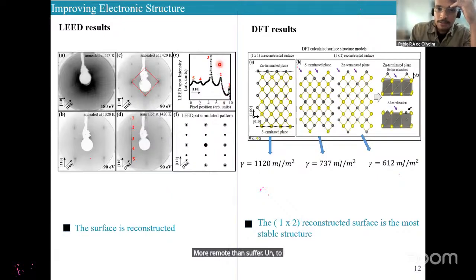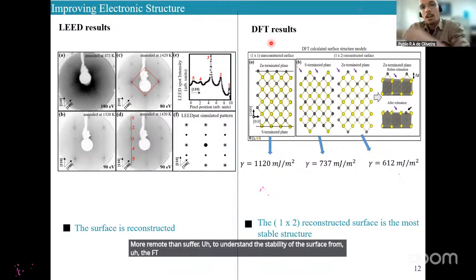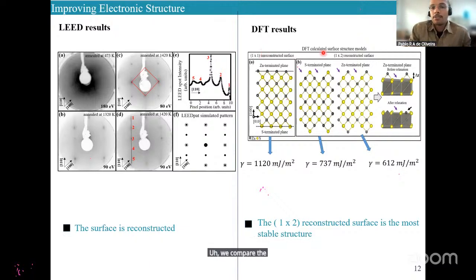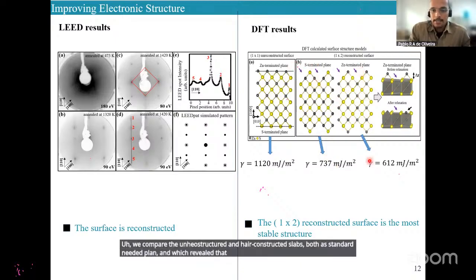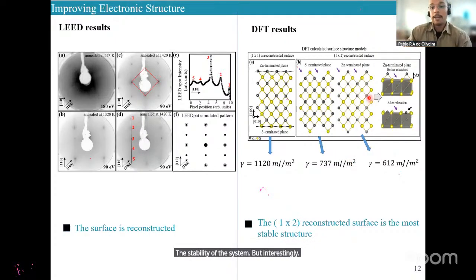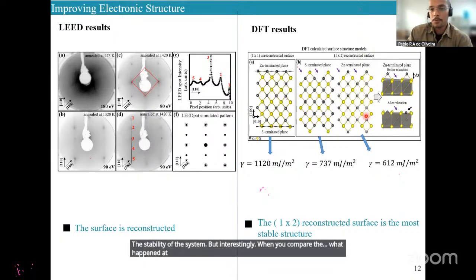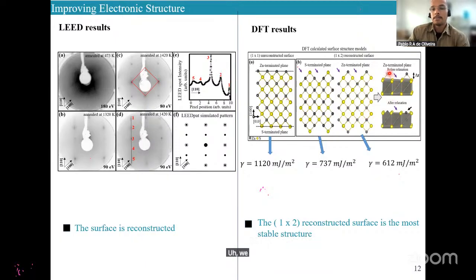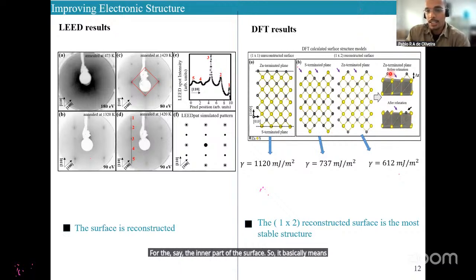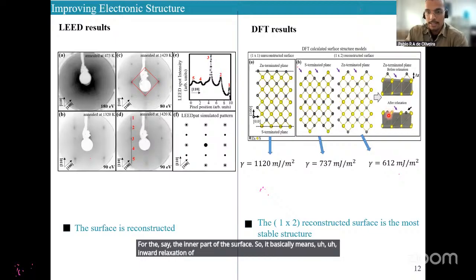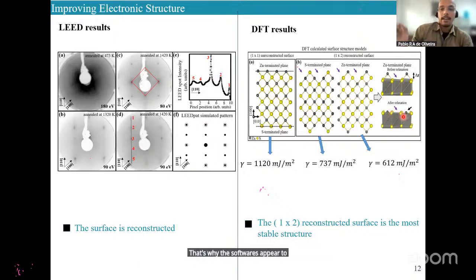To understand the stability of the surface from a DFT perspective, we compare the unreconstructed and reconstructed slab, both sulfur terminated and zinc terminated plans, which reveals that the zinc terminated plan displays the lower surface energy. So the lower the surface energy, the higher the stability of the system. But interestingly, when you compare what happened in the final relaxation process, we have the zinc atoms on top, and after relaxation, they migrate toward the inner part of the surface. So it basically means inward relaxation of zinc atoms. That's why the surface appears to be zinc deficient.